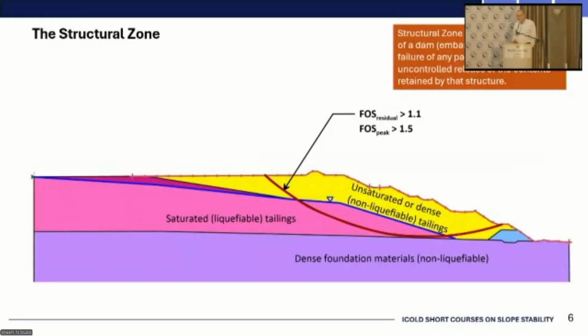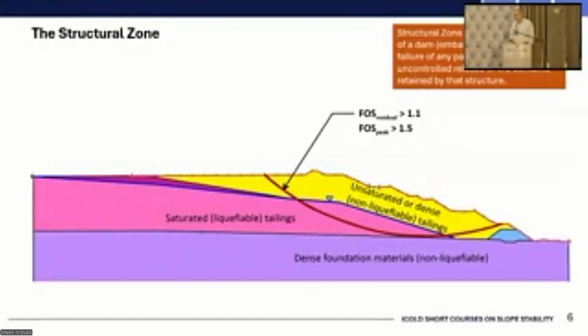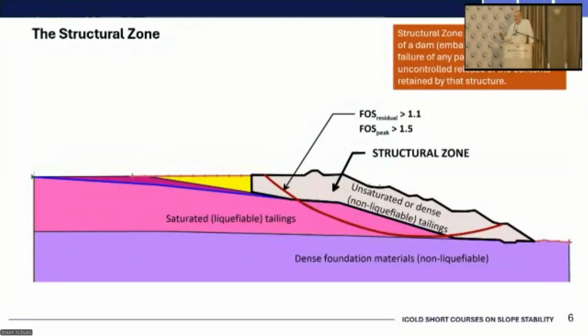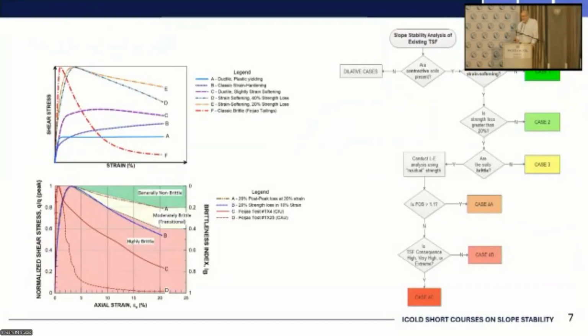So I said I would define what the structural zone is. This is a cross-section of a typical upstream method dam. The same concept applies to other configurations, but we have a fair amount of emphasis in this course on upstream methods. The yellow zone represents the outer shell that is the objective in a properly maintained upstream method dam, and it's either unsaturated so that it cannot develop excess pore pressures, or it's dense enough that it's dilative, so it might have been compacted during placement. That really forms the structural zone. The structural zone is that mass of material that is required to hold back or retain the potentially liquefied contents of the reservoir, which, with an upstream method dam, are likely going to underlie a portion of that structural zone. And as Andy presented earlier, Appendix B revolves around this flow chart on the right.